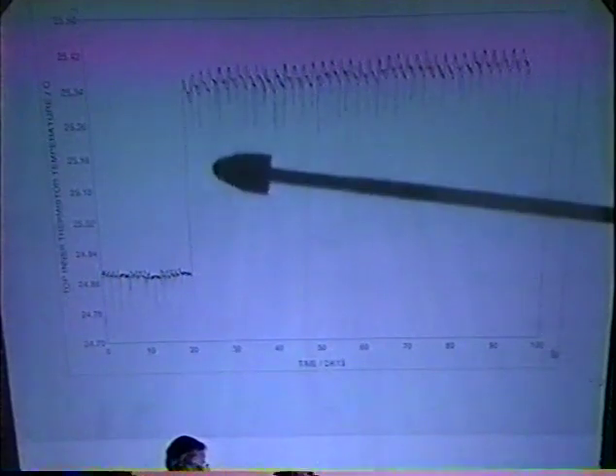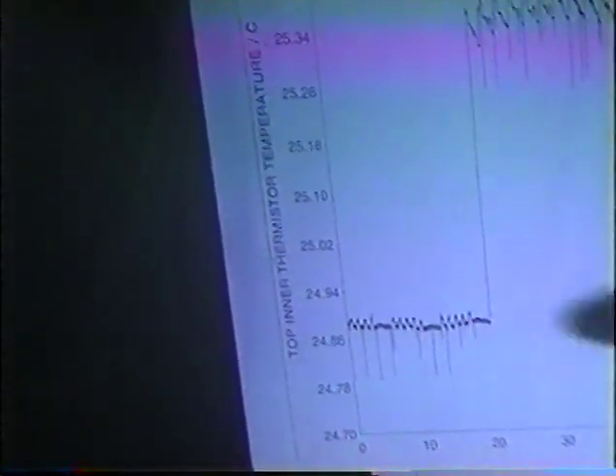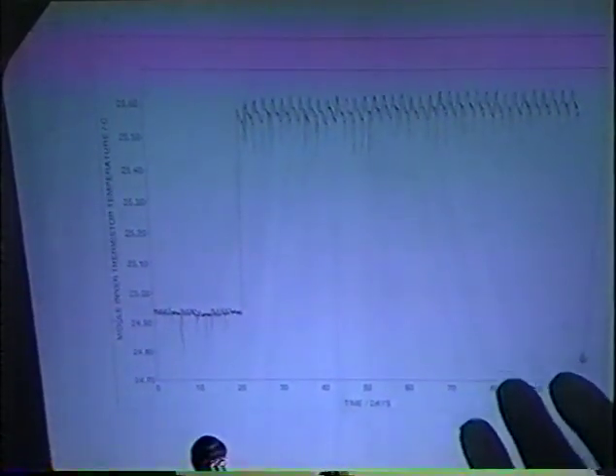You see very little difference in the bath temperature. This is the actual top inner thermistor temperature as the power is changed as a function of the method of the experiment. This experiment ran 90-some days, so that's one measurement you get. That's to be compared with the temperature of the outer thermistor located at the same horizontal and vertical position, and that temperature on the outside, of course, is always very close, within 1 or 2 hundredths of a degree of the bath temperature.